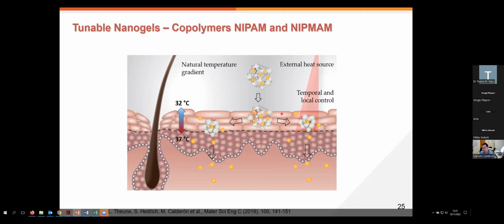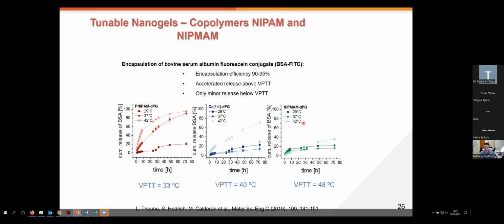And what happens if we have another nanogel where the temperature of transition is set to just only release the protein with a heat source, namely the infrared lamp? And in this case, we analyze how the encapsulation and release of the albumin as a model here fits the label albumin. And in the case we work with our nanogels with NIPAM, just as a reminder, it has a transition temperature around 34, 35 degrees.